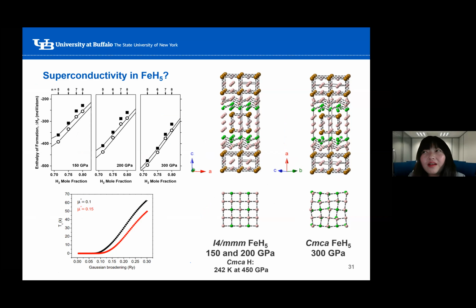Honestly, if you have a large Gaussian broadening in the output of the calculation for any system, they all become superconducting at some point, as long as they're stable, because the approximation is too bad there. So we normally would just limit the selection to very low Gaussian broadening values to make it correct. But yeah, there would be mistakes. I also want to point out that Lilia Boeri showed something exactly the same for the FeH5 structure, and her study and our study were published at very similar times.